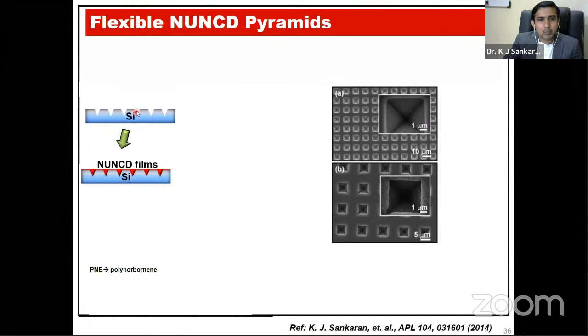First, we made pyramids in the silicon by etching the silicon material with anisotropic etching using KOH. We can achieve pyramidal shapes in the silicon substrate. So these are the pyramids here. You can see the pyramids here. It's like pyramidal holes in the silicon. And then we coated these silicon pyramids using NUNCD films. So these are the NUNCD films covering these pyramids.